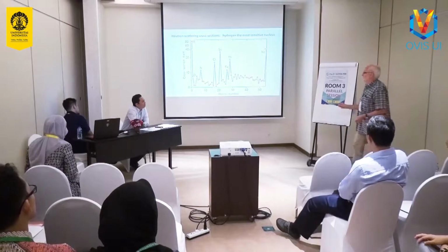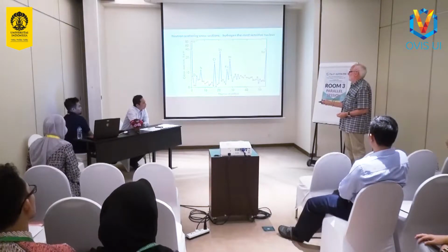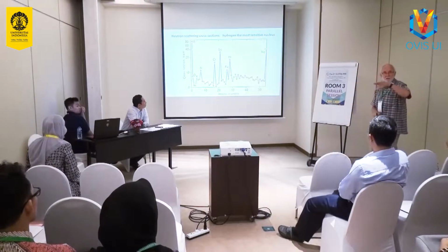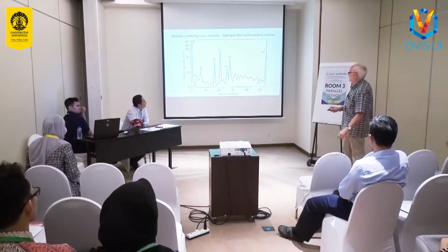If, like me, you're interested in zeolite catalysts, then silicon and aluminium and oxygen are all in here, and their scattering cross-section for neutrons is negligible compared with the proton. That means when we look at a zeolite, we don't see the zeolite. All we see is the hydrocarbon or the hydrogen-containing species in the zeolite. An excellent sensitivity for hydrogen.